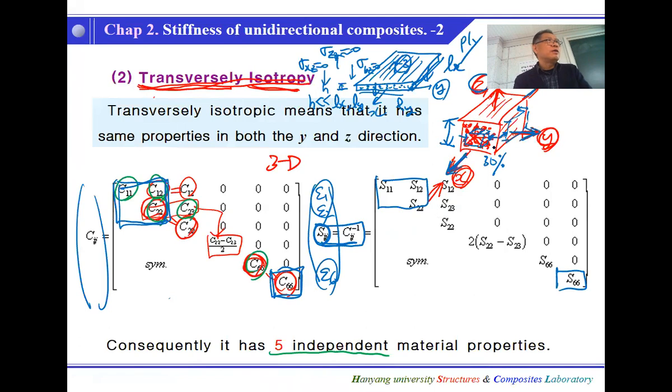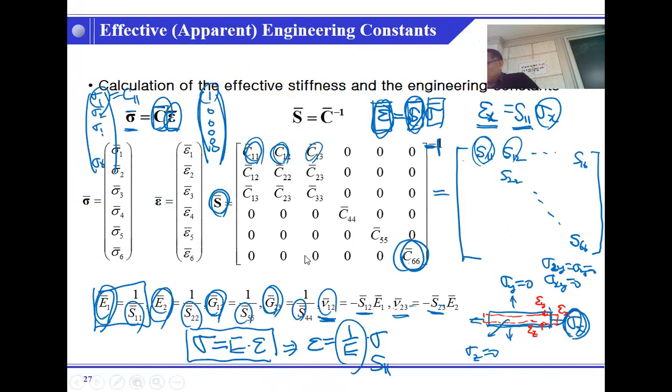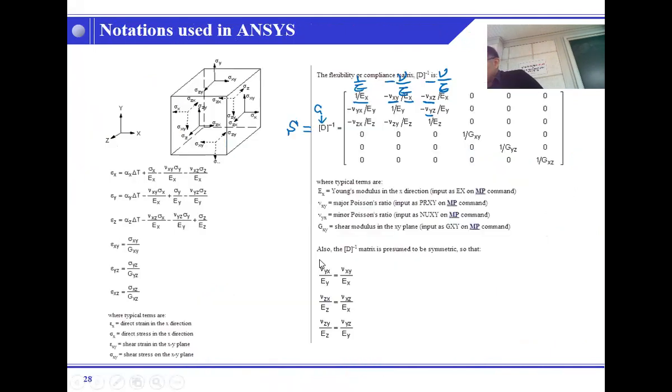How small? Well, for example, this EX is 100, and this EY, I would usually say 10. Then the 30% is 0.3, and this contraction will be 0.03. That is about the order. And simply, I will use this notation. Okay, I will just use this one.